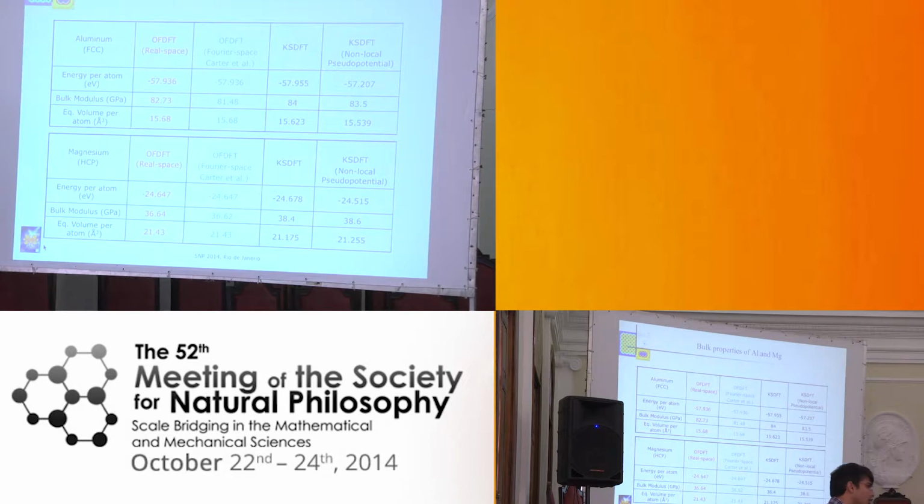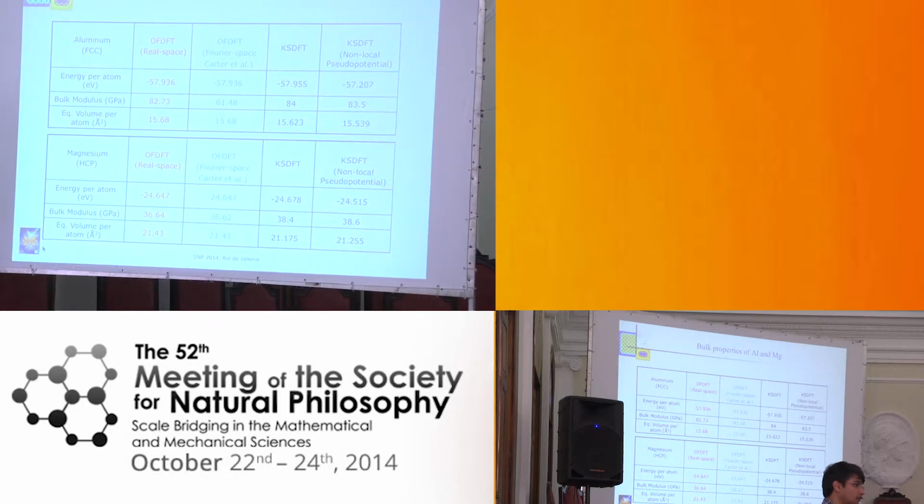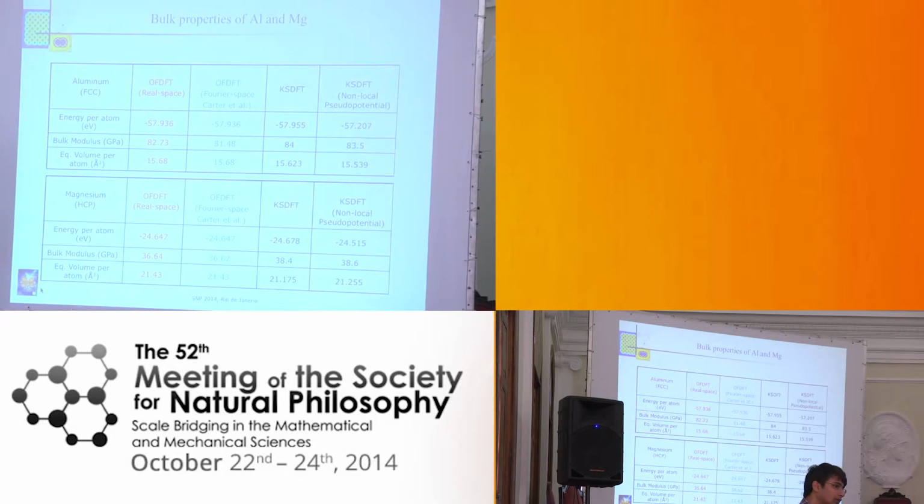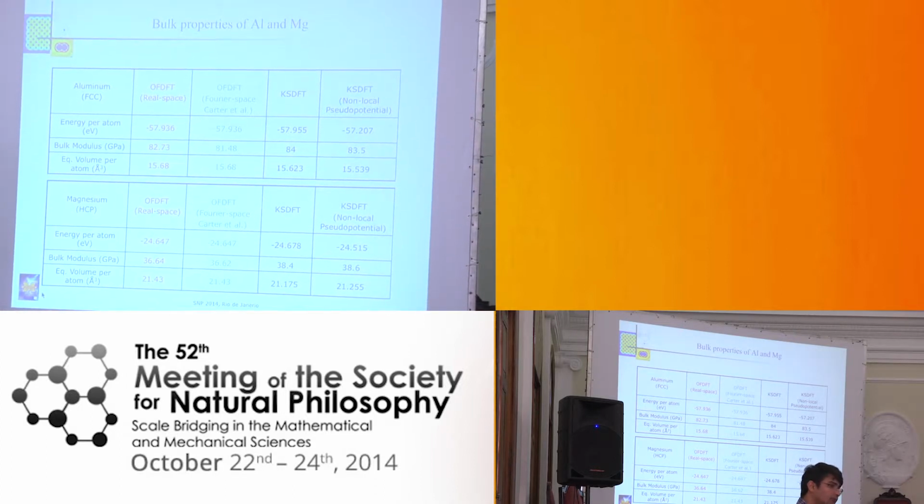In all these calculations, we use what is called a pseudo potential. The nuclear potential is a Coulomb singular potential if we have to treat the nucleus in its full glory. But in material science, what matters is only the treatment of the valence electrons. In a few cases, there are scenarios where even the core electrons play a very important role. So often in density functional theory, people do pseudo potential calculations, where the effective potential of the nucleus is given by the nuclear potential and the core electrons, so that only the valence electrons need to be solved for.